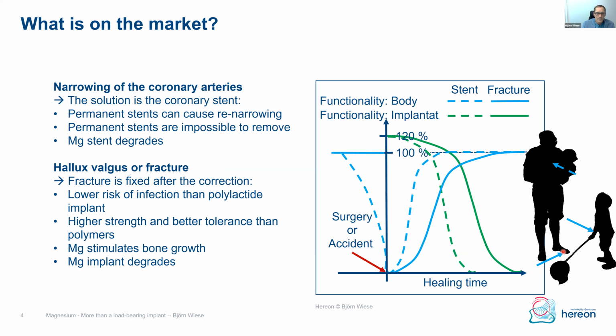They like it more than the other way around. It has a higher strength and ductility, which I already mentioned, and it's better tolerated in the body because of this environment change. At the same time, it stimulates the growth of new bone at such a fracture site, which improves the healing during the degradation. With time, it degrades, and that's quite important for kids.